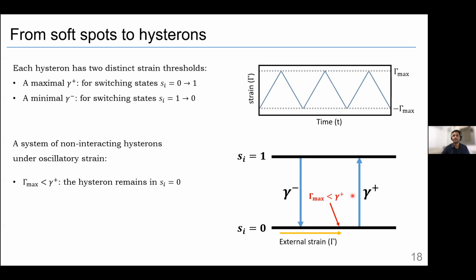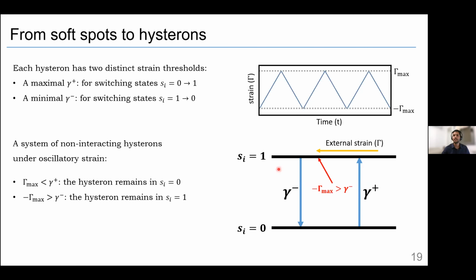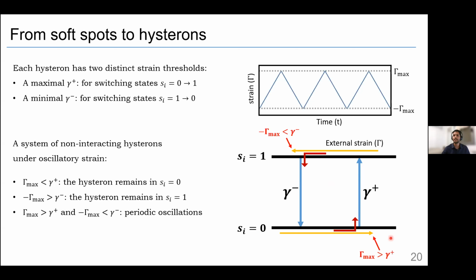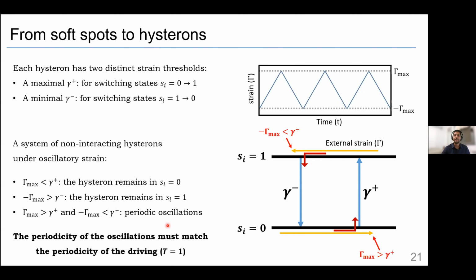And if you have a system of non-interacting hysterons, you apply cyclic driving between gamma minus and gamma max. You see that if gamma max is below gamma plus, it will remain always in S equals 0, it will not switch ever. And similarly, if it cannot reach gamma minus, it cannot switch. It will remain in S equals 1. But if gamma max is bigger than gamma plus, you can switch from 0 to 1, and again from 1 to 0 if it surpasses gamma minus. So this will create periodic oscillations. And this periodicity must be equal to the periodicity of the driving. It cannot be multi-periodic. We call it T equals 1.